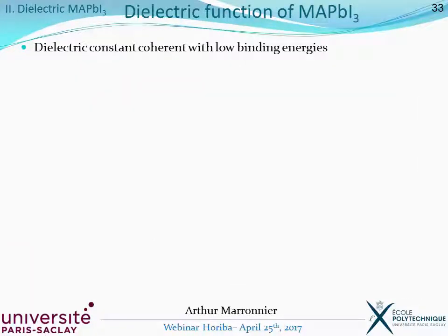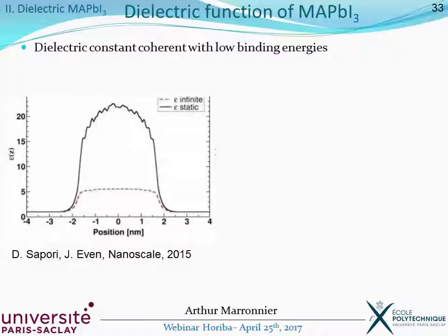So we found that for the hybrid perovskite, the dielectric constant is coherent with low binding energies, which could explain why it has such good electrical transport characteristics. This is also coherent with the literature. In 2015, some values from calculations of the epsilon constant in both frequency regimes were published, and you can see a value around 20. This value is coherent with what we found.